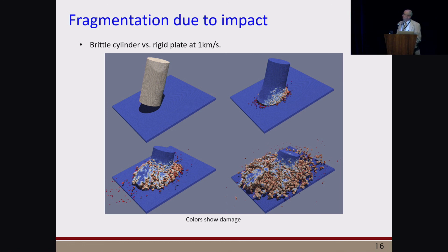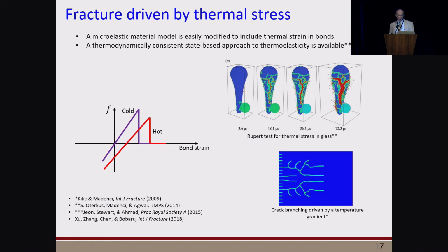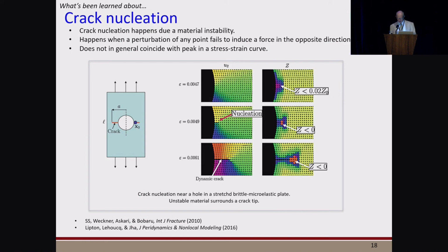Fragmentation is another natural application of this method because you can simulate a lot of mutually interacting cracks without having to specify the growth of each one according to some external criterion. Other applications include thermally driven cracks, such as this interesting pattern that is obtained in glass, in which there is a temperature gradient from left to right. And this is a simulation that some researchers at Corning did, studying the residual thermal stresses in glass.